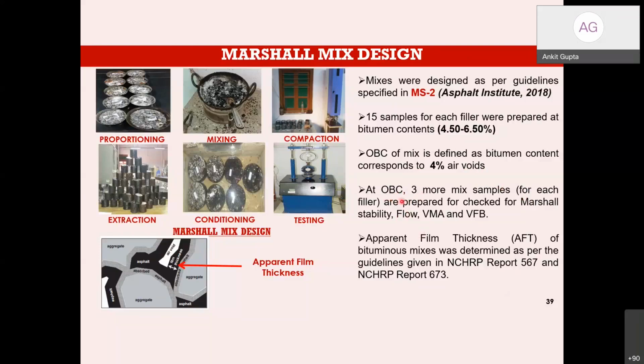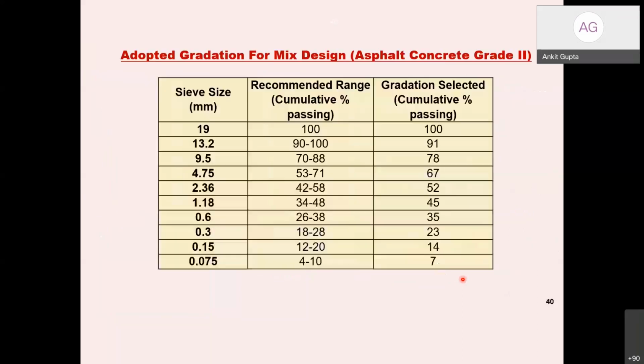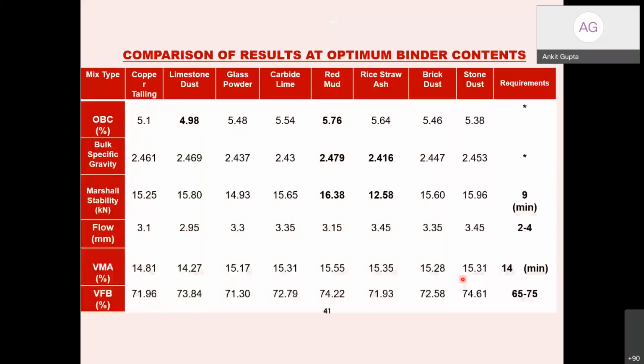And at OBC, 3 more mix samples are prepared just to check the statistical or repeatability values for finding out the Marshall stability, flow, VMA, and VFB. We also tried to find out the apparent film thickness, that is, the film thickness around the aggregate, with respect to NCHRP report 567 and 673. We have used BC grading 2 for the asphalt grading, which has been taken from the Ministry of Road Transport and Highways guidelines, that is the Orange Book. And these are some of the comparison of the results for the Marshall mix design.